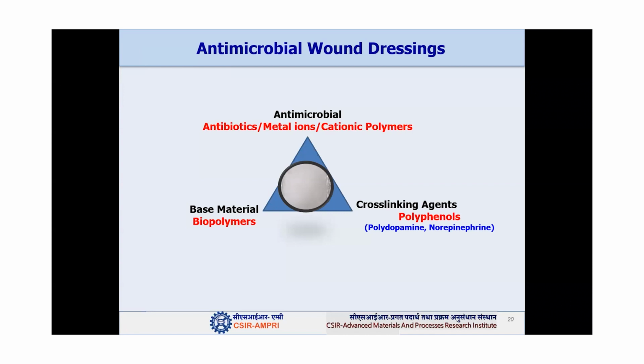A biopolymer has one drawback: they are soft polymers and they can easily degrade. So we also need a cross-linker for these biopolymers. For the cross-linking agents, in our case, we have used benign cross-linkers. One is polydopamine and another is norepinephrine. These two compounds we have used as cross-linkers. Soon I will show why we have used these particular compounds. Here I also want to mention that we are the first, you can say, who discovered polydopamine and norepinephrine as benign cross-linkers for biopolymers.